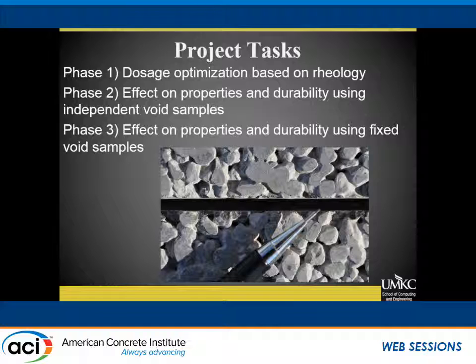what's happening here? So the first one is some rheological testing on just the paste. Second phase was, if we are going to place these, what are the properties and durability, assuming we have independent void samples? So we're going to control the compaction method like we do in the field, and we're going to let the void content float depending on what the effects are to workability. And then the third phase is to compare those effects. Let's control for the voids and see what the response was.